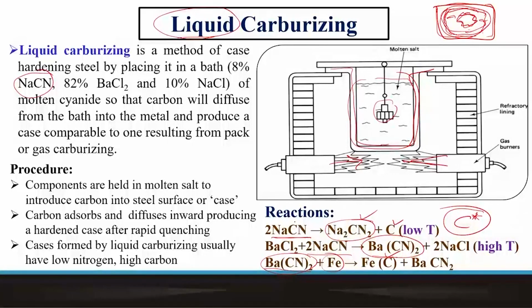This is more possible at lower temperature, but when we are dealing with slightly higher temperature, then this sodium cyanide can react with barium chloride, another salt present in the charge, and form this barium cyanide, and barium cyanide in turn can react and dissociate at the iron or steel surface and contribute to nascent carbon for diffusion. So this is the bath composition, and as I said, this is a molten or a liquid bath, and so we have to hold the component inside the bath so that we can enrich the surface or create a case of carbon enriched surface. And this is usually a carbon enrichment process, and obviously will have very low nitrogen content. But in some cases, certain amount of nitrogen dissociation and adsorption at the surface is also possible.